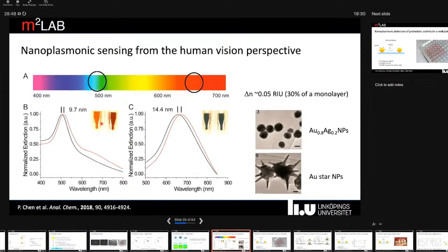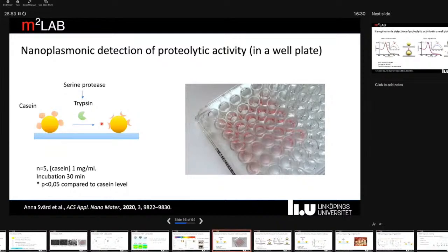But in most cases, we have access to a simple spectrophotometer of some kind. For example, in most labs, there are plate readers available. And plate readers use well plates as a carrier of samples, which come in various shapes and forms, but they are typically always made of plastics. And since we can immobilize particles on plastics, we can turn these well plates into LSPR sensor surfaces. And that's what you see here.